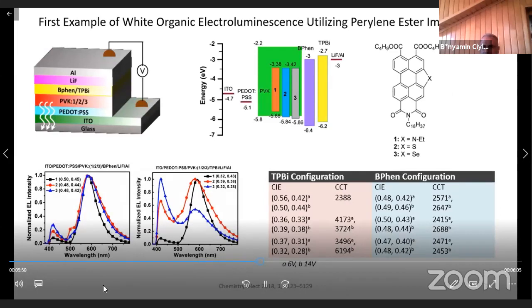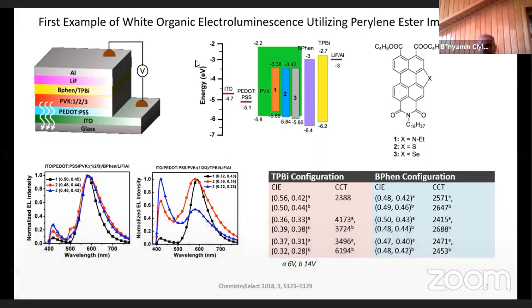Three different perylene derivatives were used as red-orange emission material in the study by Qubit et al. Perylene derivatives were doped into the PVK host and two different electron transport layers were used. Electroluminescence intensity of the blue emission is higher in the case of the TPBI-based device as compared to the BPhen-based device. A lower electron injection barrier at the PVK-TPBI interface results in more electron injection at the LUMO level of the PVK, resulting in more blue emission from PVK.